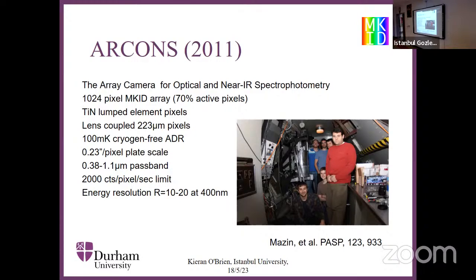One of the things I should say is that these are superconductors, so one of the challenges to some degree is that we have to cool these to sub-Kelvin temperatures. We typically operate the devices at around 100 millikelvin. As you can see on the left-hand side here, this is our little ADR fridge, which enabled us to operate at 100 millikelvin for the best part of the night.